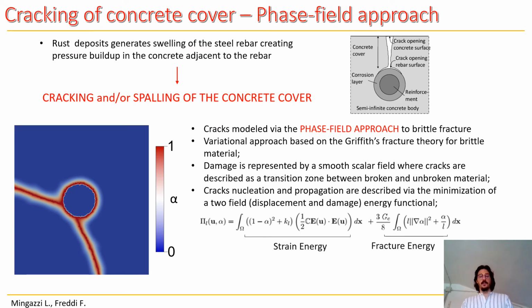Once the value of the swelling associated with the formation of rust deposits is known, we can proceed to describe and model the cracking or spalling phenomenon of the concrete cover, and we choose to approach this problem via the phase-field approach for brittle fracture. In particular, this is a variational approach based on the Griffith theory of fracture for brittle material, where damage represents a transition between the broken and unbroken areas of material and is represented using a scalar smooth field.